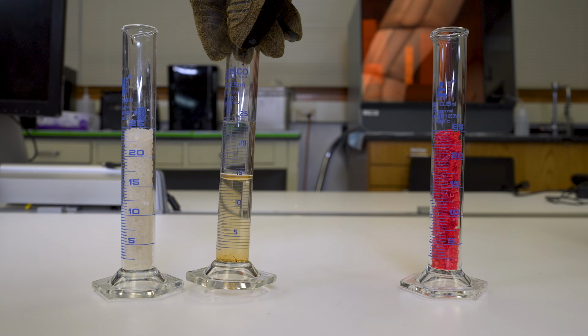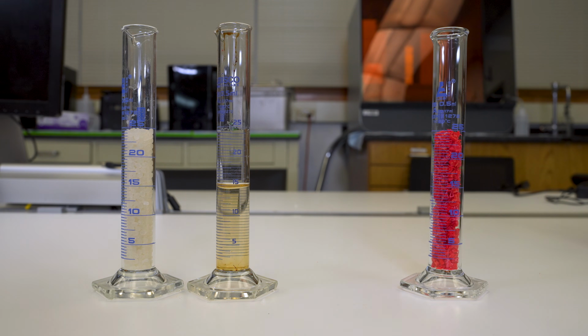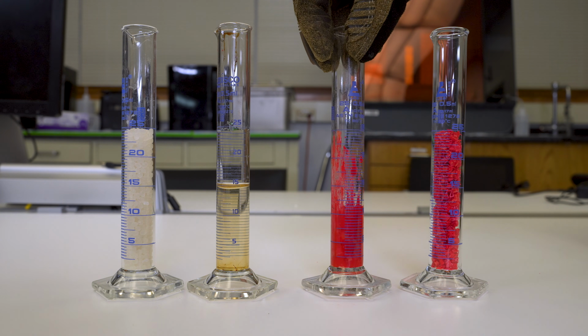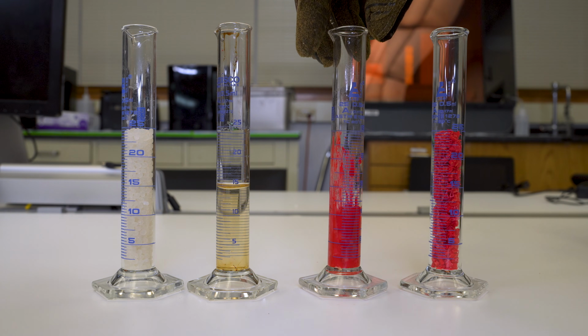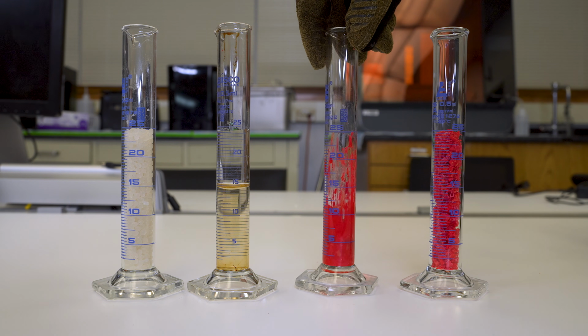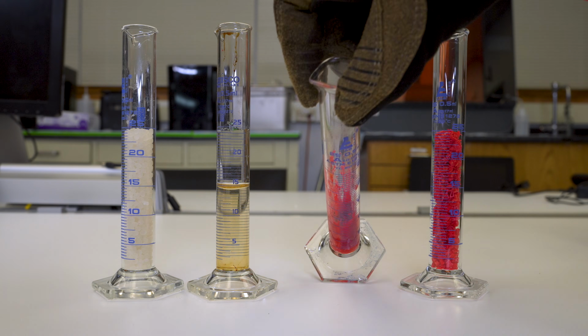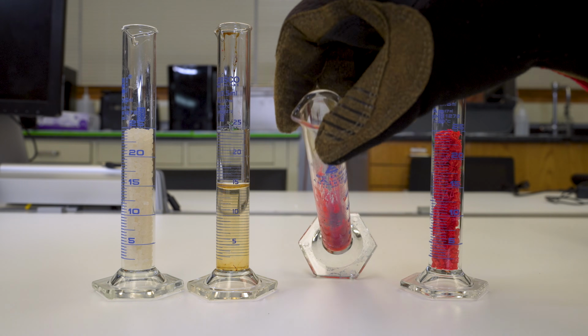Here you can see that when 25 cubic centimeters or 25 milliliters of pellets are melted, they take up about 15 milliliters. The regrind, on the other hand, doesn't yield as clean of a result, but estimating for the material on the wall and the void in the middle, there is likely 8 to 9 milliliters of melt.